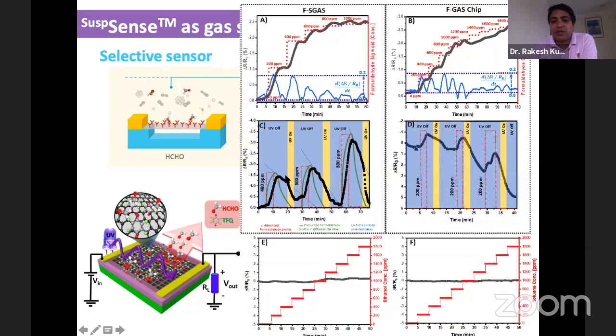Pictures C and D show how fast you can recover a suspended graphene sensor compared to a supported graphene sensor, which does not show any recovery. Rather, it damaged the graphene when it was irradiated with the UV light. This has a specific application in real-time air quality monitoring, where you need to monitor the real concentration level. If it goes up, the sensor should show a higher concentration signal, and if it goes down, the sensor should recover automatically. We have validated our results against methanol, toluene, and also acetone. Once it's coated with a specific material, it does not show any sensitivity towards non-selective gases. So that proves its specificity.